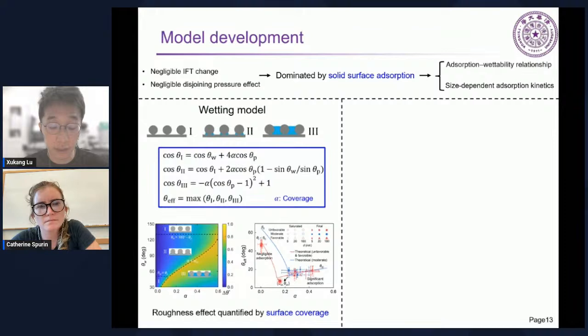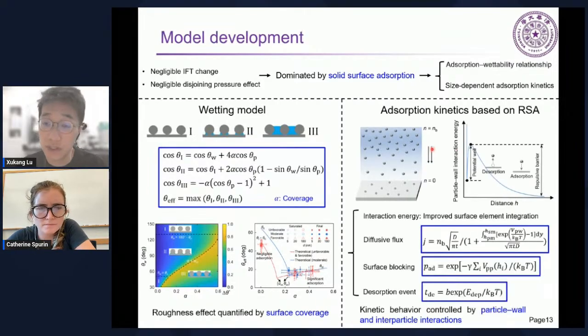And then we have this non-trivial relationship, and it fits well with the experimental data. But you can see the data distribution is kind of sparse and scattered. It does not distribute uniformly along the theoretical line, and that is induced by the microscopic adsorption kinetic feature. The adsorption kinetics is a little bit complicated, but the essential physics is a diffusion process driven by the concentration gradient, and it is strongly affected by particle-wall and interparticle interactions.